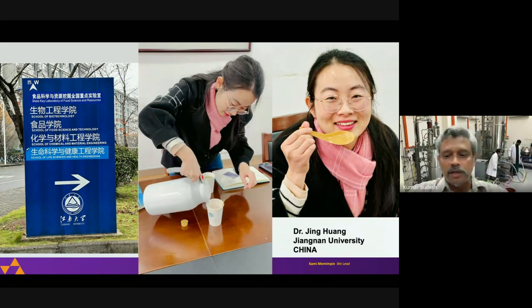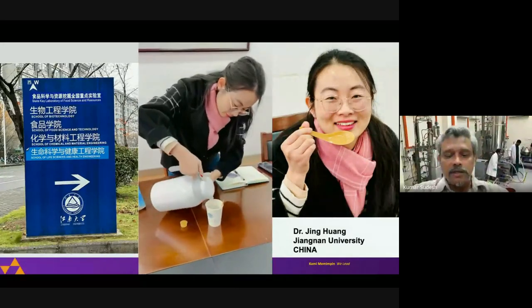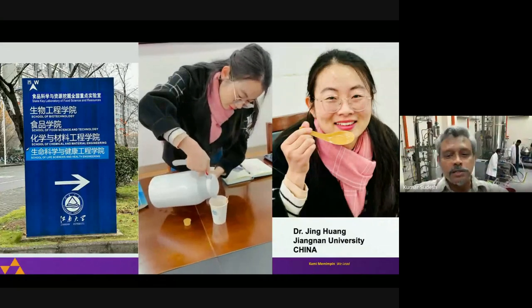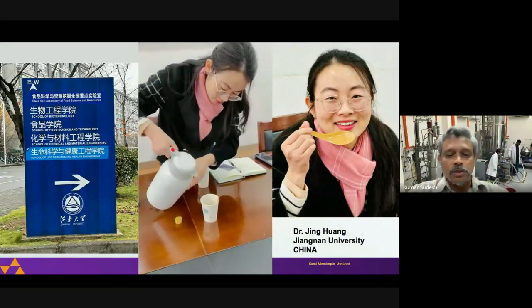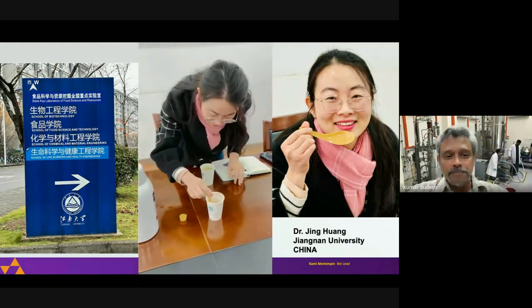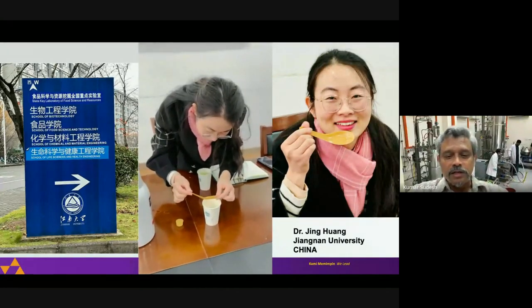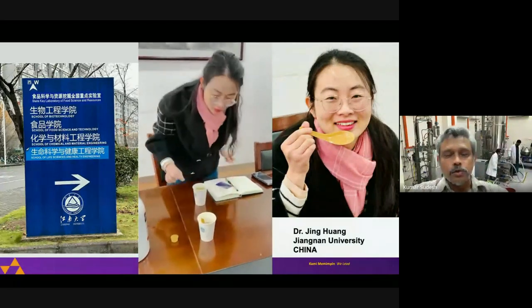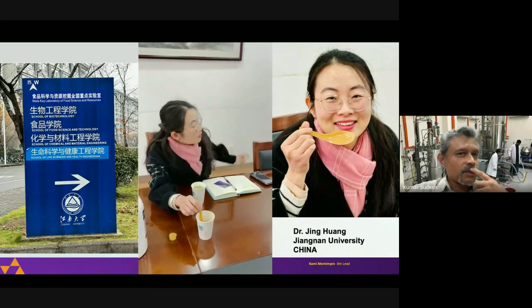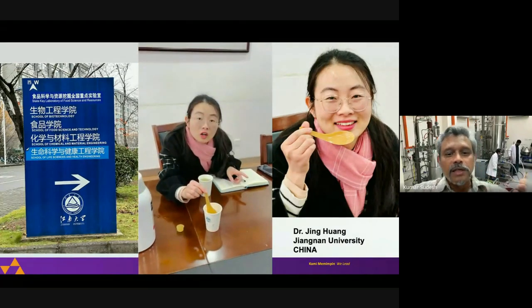So this is in one university in China, where the researcher there wanted to check the thermal stability of PHA spoon. So what this researcher did was to pour hot water, which is close to about 100 degrees, and to see whether the plastic is still strong. Because some plastics are not thermally stable, and when it is put in hot water, it melts or it becomes soft, and it's not suitable for hot conditions. But PHA is very thermally stable, which means that you can use PHA even in close to 100 degrees Celsius.